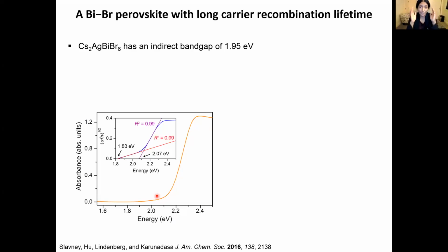And the reason you can get away with a thick layer is because the photogenerated electrons and holes have a very long carrier lifetime, so that they can find their way out of this really thick layer and find the current collector. So the question for us is, what about the silver bismuth double perovskite? Does this material have long-lived carriers?